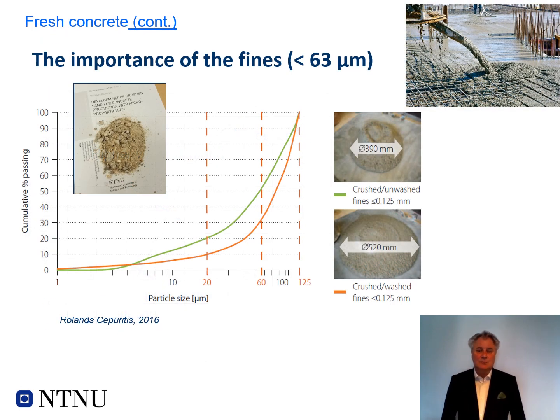As an example, we have here a work by Rolands Cepuritis. He finished his PhD in 2016 at NTNU in Trondheim. He looked at different types of aggregate, manufactured sands and so on. In this case, you can see that he took the same aggregate from 125 micron and coarser, the same grading, so it's not included here. But from 125 and down to finer, you can see he used two different fillers, two different fines. The orange one is crushed washed fines, while the green one is crushed unwashed.